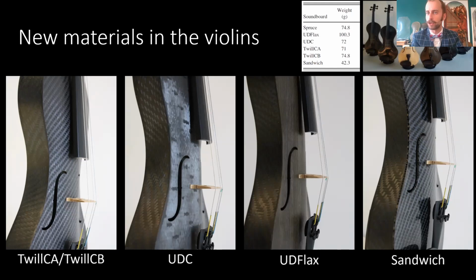But the composite materials, the unidirectional flax, you have to add a lot more for it to be stiff enough. So you end up with a very high weight, 100 grams for the top plate. The unidirectional carbon and twill CA are about 72, 71 grams. Twill CB was a little bit more. So you see that with this method that I have shown, the twill CA and the twill CB, I have tried to make them the same, but they're not completely identical. So there is a minor difference between the two.